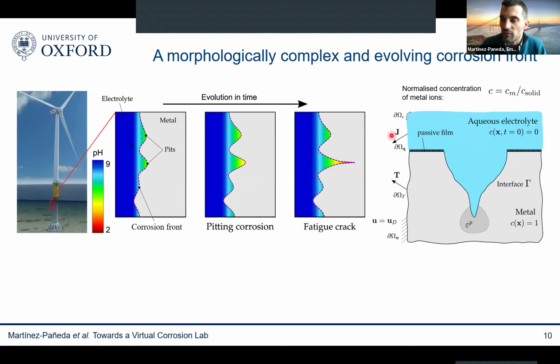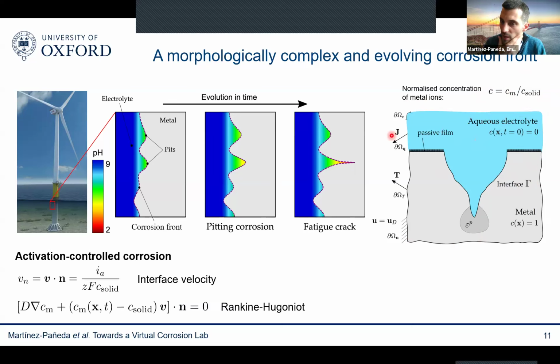in the electrolyte. And if I want to then describe what corrosion happens, I can have two situations: activation control corrosion or diffusion control corrosion. If I am under conditions of activation control corrosion, then the evolution of the pit, the velocity of the pit is given by this equation, which is again Faraday's second law. So you have the current, the concentration of the metallic ions, and then the concentration of the metallic ions in the interface is given by this Rankine-Hugoniot condition.